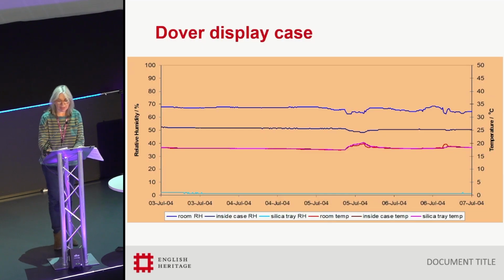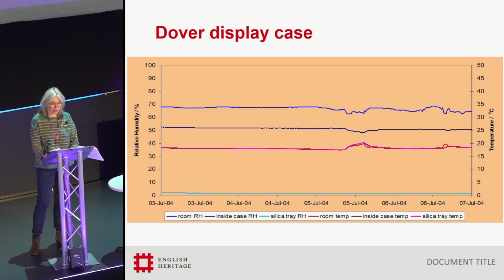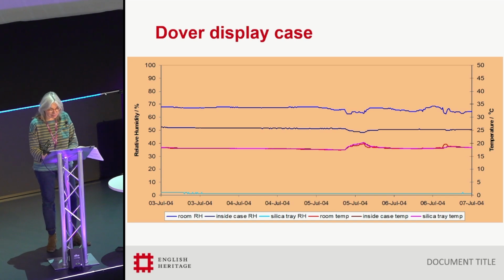So for some passive control air movement case studies, this graph shows a case at Dover Castle with a solid baseboard with a small gap around its edge. It doesn't work. There isn't enough air movement from the silica gel unit into the main display area. So the top line shows room RH, which is in the 70s. Below that you have the display case RH in the 50s. Then red and pink line is temperature. And then the light blue line at the bottom is the silica gel unit RH, which is less than 5% RH. So we have 5% in the silica gel compartment and 50% in the display volume. It's not great.